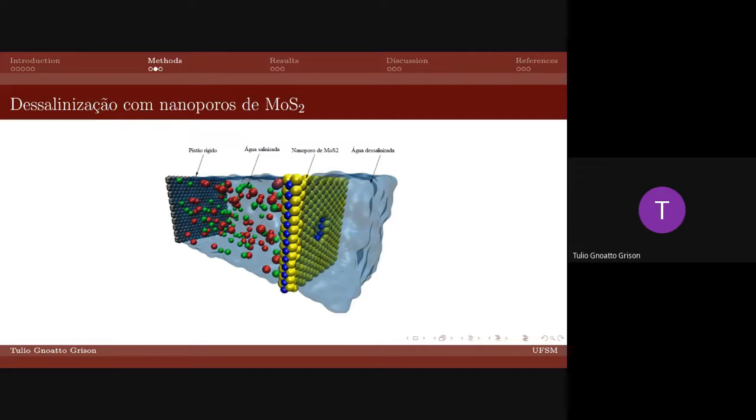The temperature is constant at 300 Kelvin and a pressure of 180 megapascals. The simulation box is 4x4 nanometers in the plane of the membrane, and 30 nanometers in the direction normal to the membrane. Periodic boundary conditions were used in all three directions.